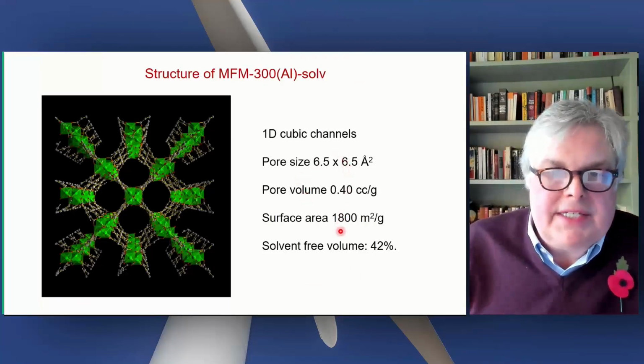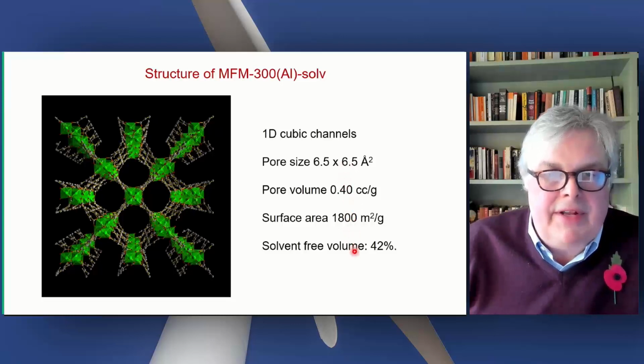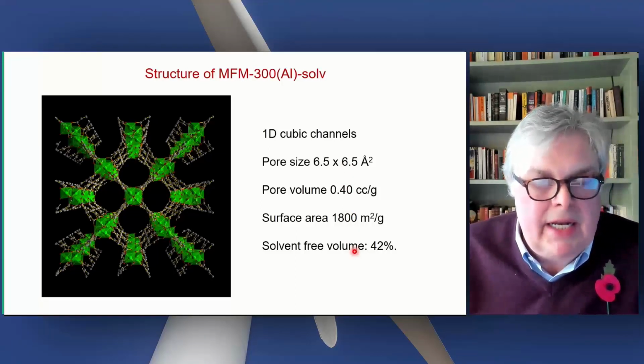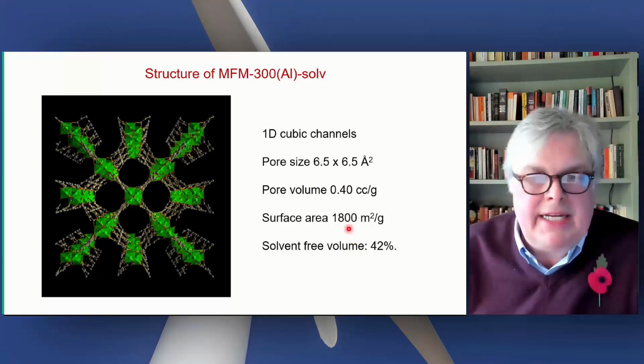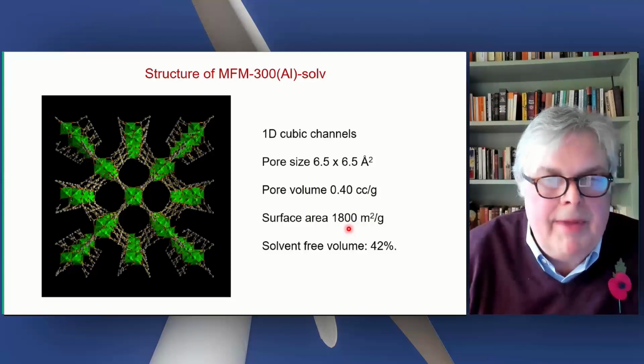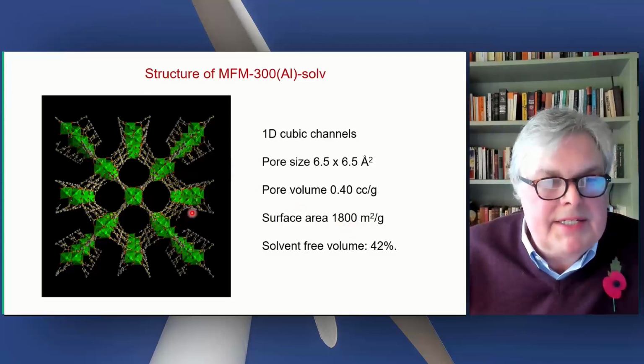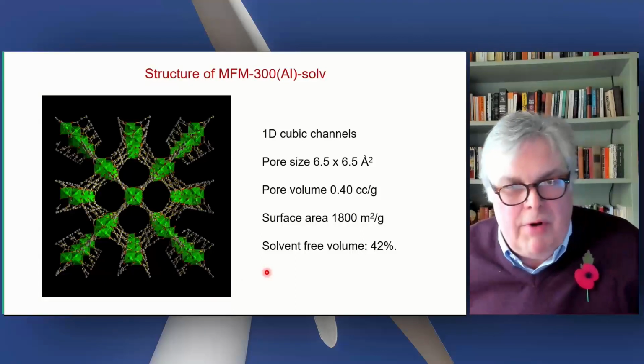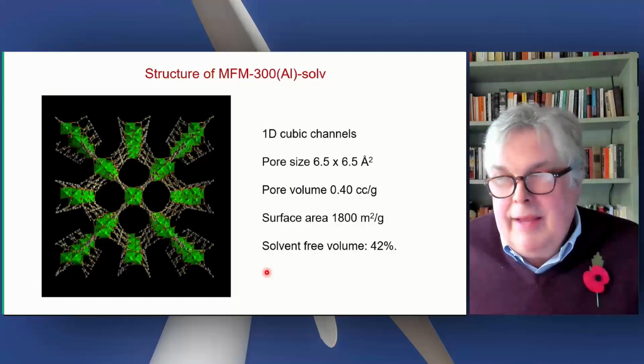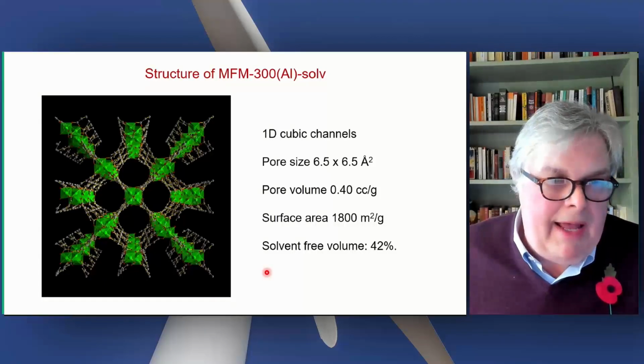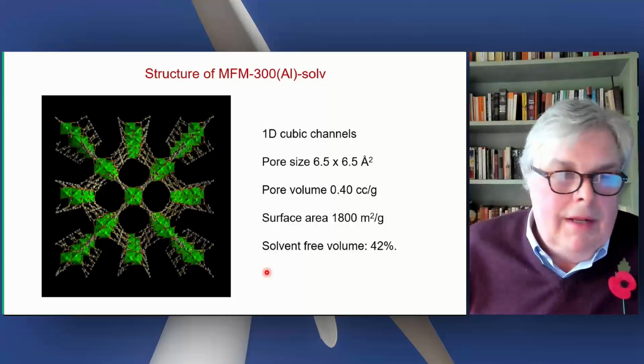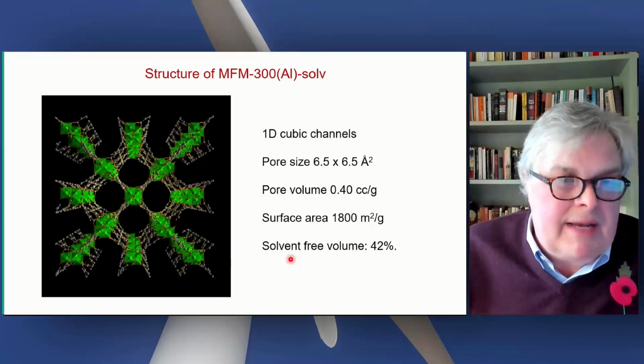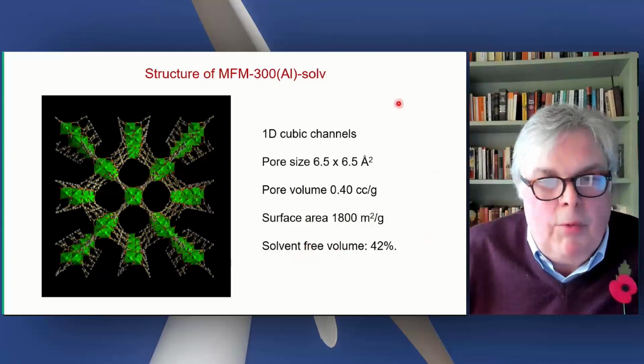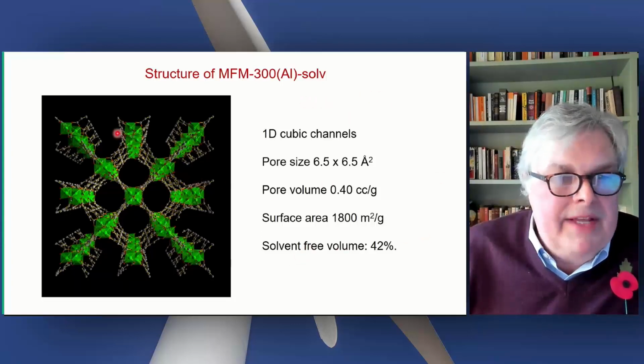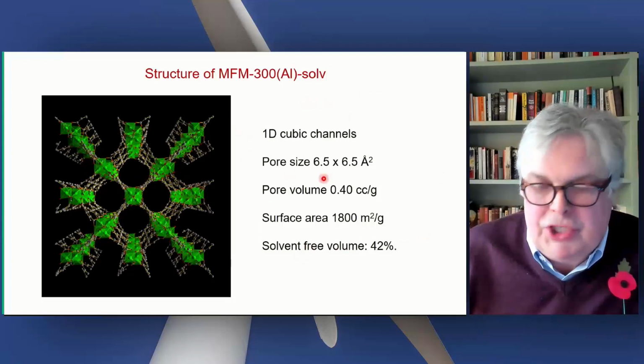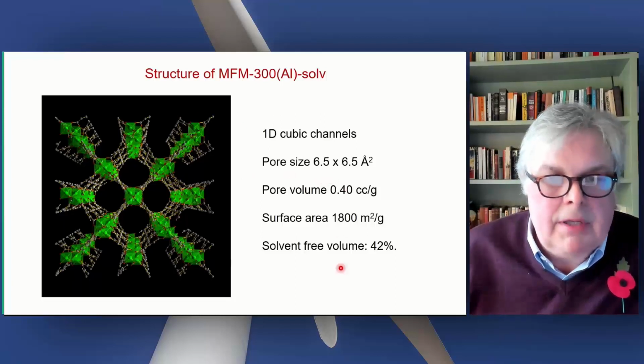The pore sizes and various data are given here. This is not a particularly porous material, 1,800 square meters per gram. It is extremely stable. So this is the other feature of MOFs that people believe. They believe they're very expensive to prepare, cannot be scalable. In terms of expense, of course, some are expensive, but we can scale these up. And this material and other MOFs that I'm going to show you are extremely stable.